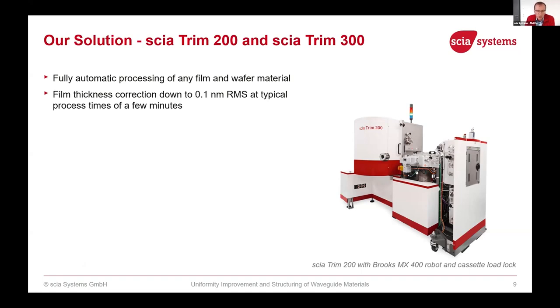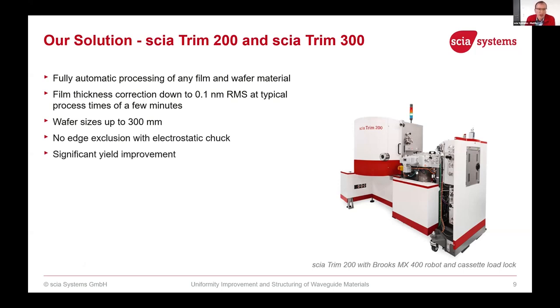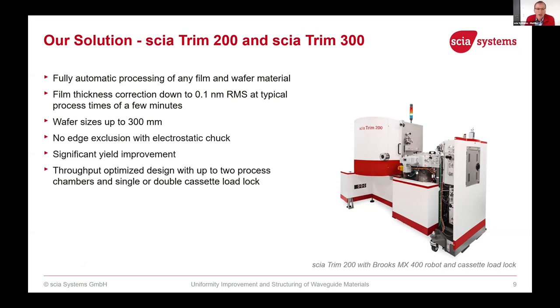The film thickness correction could be down to 0.1 nanometer RMS. Typically, the processing takes a few minutes. Wafer size up to 300 millimeter, I mentioned already. No edge exclusion, since we have an electrostatic chuck that exposes the full wafer surface to the process. And with that, you can achieve a significant yield improvement, and a throughput optimized design with two process chambers is also available for high throughput manufacturing demands.